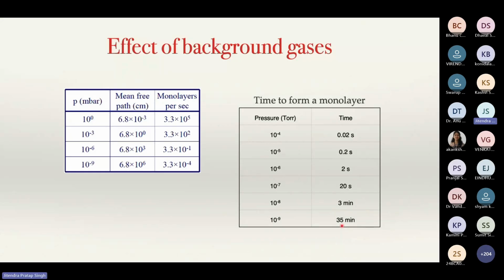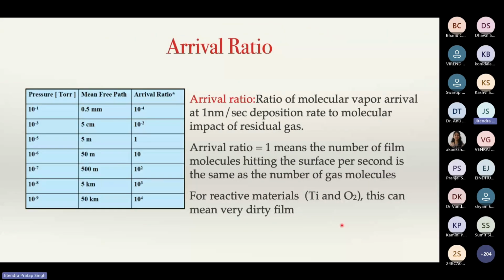Now the other thing, which is very important: mean free path and pressure are very important parameters when we want to fabricate maybe a device or the contacts. The other thing is the arrival ratio also. In case of deposition, arrival ratio means how many molecules arrive at 1 nanometer per second deposition rate, relative to the molecular impact of residual gases. Even if my pressure is 10 raised to power minus 6 torr, in high vacuum, or even low vacuum, it doesn't mean that there is no other gas.